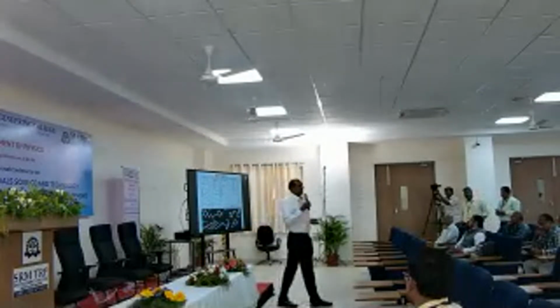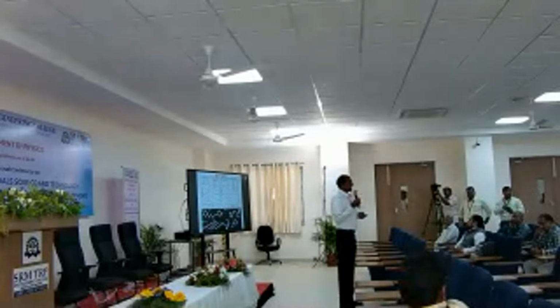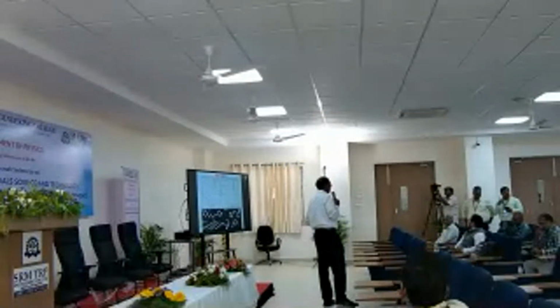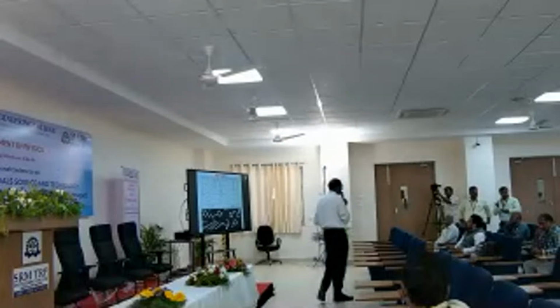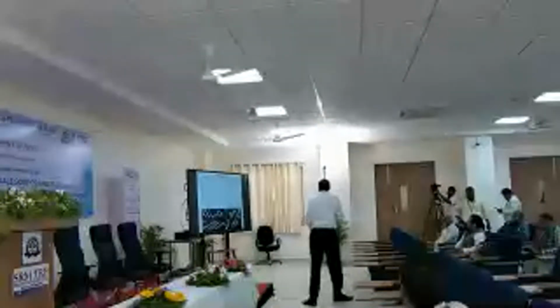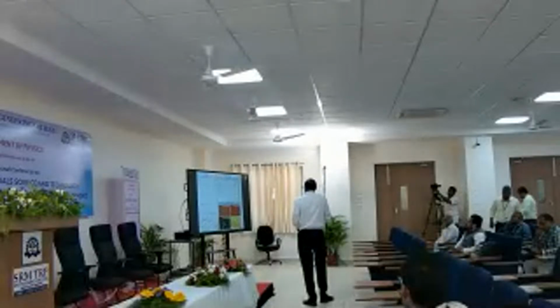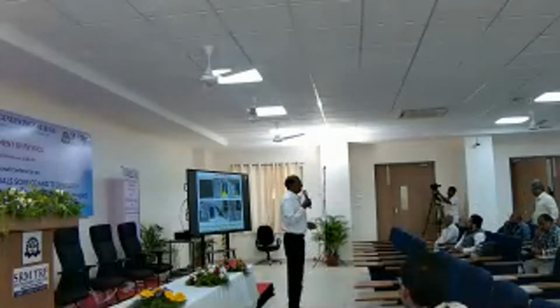And then we did all the essential characterization. We also did some molecular simulation studies to fix the annealing temperature, because we cannot use chemical reduction here as it will damage the physical structure. So we use inert atmosphere annealing like argon or nitrogen, and to fix the annealing temperature we did some molecular simulation studies. This is actually the actual bucky paper, which is 10 square centimeter area.